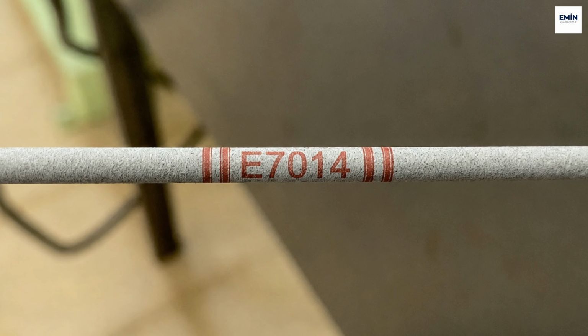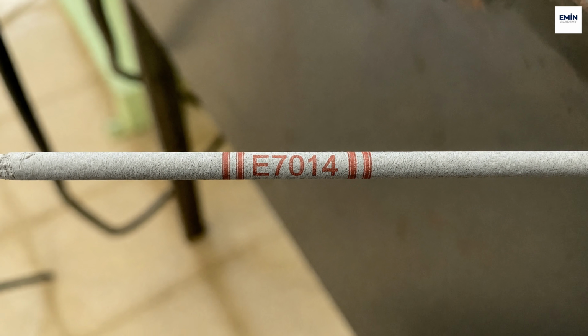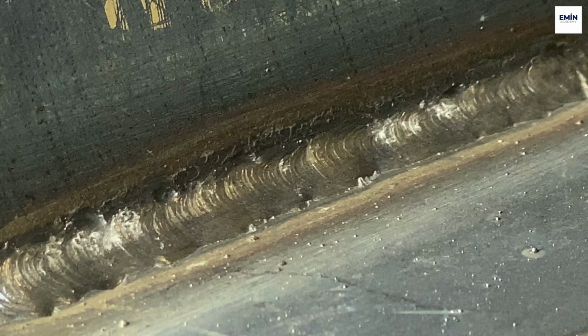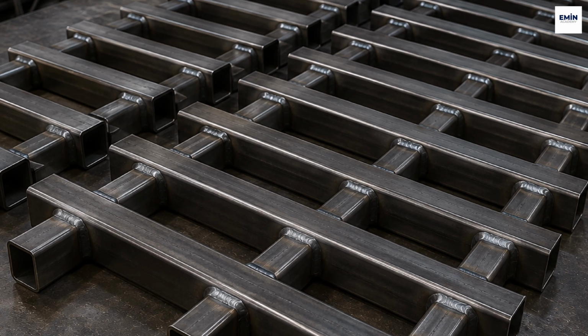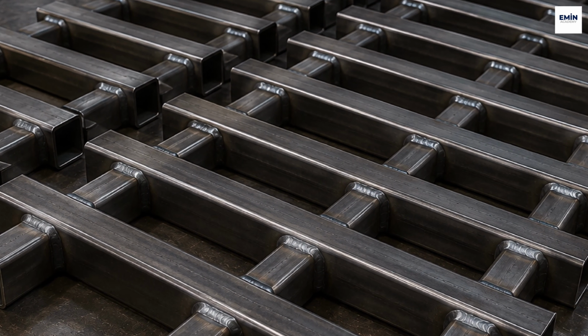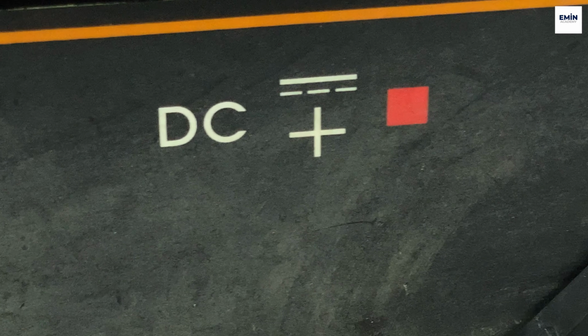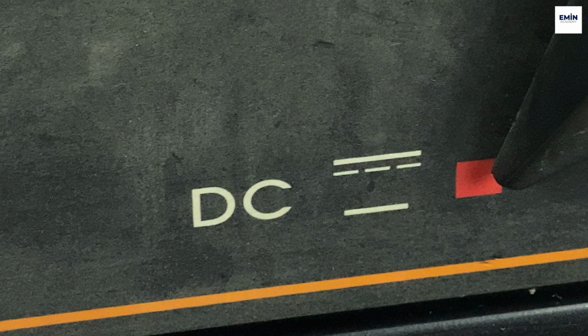4. Rutile-coated electrode. The E7014 electrode is an example of this. Since it contains iron powder, the weld metal deposition rate is higher. It's generally used for fast filling, general fabrication, and mass production welding. It's suitable for alternating current, direct current electrode positive and direct current electrode negative polarity.